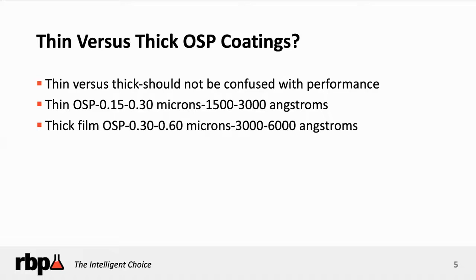So you will see in various specifications, you'll see 2 thickness ranges for OSP. One I refer to as thin, which is typically between 0.15 and 0.3 microns. And the other is thick, between 0.3 and 0.6 microns. Again, it is up to you as a fabricator and as an OEM who may be specifying OSP for your boards to check with the supplier and the fabricator using these processes whether or not these are truly solid coatings that minimize, again, the effect of oxidation and humidity. So again, the technology says thin and thick both work, as long as the key is preventing oxidation penetration to the copper surface.